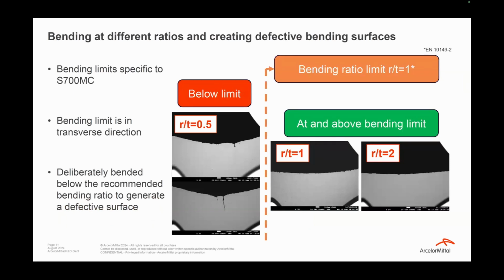So then what we did is first bend the S700MC with different bending ratios. If you check the EN standard, you will see that for 700MC, there is a bending ratio limit R/T equal to 1, so that you shouldn't go below it. If you go below, then you're gonna create defects in your bend profile. It's gonna be too rough, so that it's not really suited. For this study, we deliberately bent below the recommended bending ratio to generate these defective surfaces, because we would also like to get an idea of how they're gonna underperform, and they should underperform, and then how it's gonna affect our quality assessment.